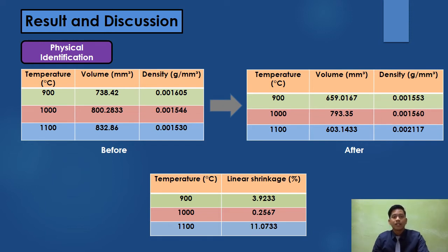For the linear shrinkage result, the sample linear shrinkage was 11.07% at 1100 degrees Celsius, which is the largest linear shrinkage percentage, 0.26% at 1000 degrees Celsius, and 3.92% at 900 degrees Celsius. Previous research found that when sintering temperature increased, sample linear shrinkage increased.